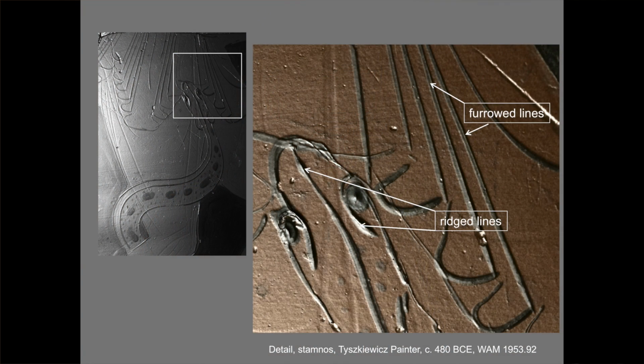If one looks at these lines under high magnification, one can see that actually there are two distinct line types. The longer lines which are continuous and fluid have a distinct furrowed profile. So right here, these lines. While the shorter lines, which are less fluid and often have a turn in the line, are especially thick and high and have a profile with a single peaked ridge. See here? In order to better understand what tools created these distinctive lines, it was essential to first characterize them. This was done with the help of two instruments which had not been used to study Greek ancient vases before.